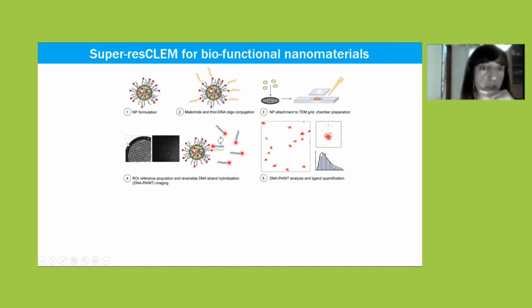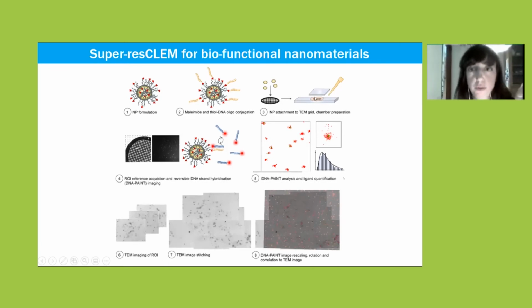And then, well, first, because later we will do correlative, we need to know in which grid hole we are imaging. So this is important to acquire some bright field images and to learn in which grid hole you are. Then you do all the DNA paint imaging to get information on the number of ligands on the surface of these nanoparticles. Then you take the grid out of the chamber, you do negative staining, and then you go to the TEM to do TEM imaging. And then later on you stitch all these images and perform the correlation.